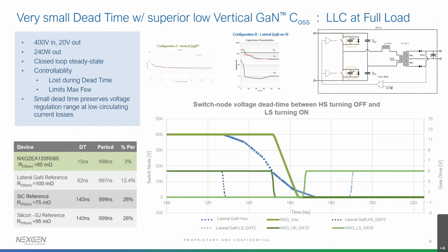First of all, if you go to higher switching frequencies, you're losing more and more of your cycle where you don't have the whole system under control. So the controllability is an issue. And if you spend much more time in dead time, then the gain of the LLC stage is compromised, is lower, and you lose some of the regulation capabilities. Of course, you can make it up by increasing the circulating current, but when you increase the circulating current in order to bring down the dead time of your LLC, then you increase the I²R losses.